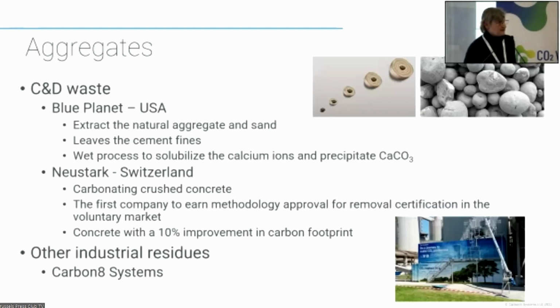So in the aggregates field, again, people using C&D waste because of it being in abundance, and Blue Planet in the USA extracting the natural aggregates and sand from the concrete and demolition waste, and then solubilizing the calcium ions from the cement fines and precipitating calcium carbonate to make nice limestone, what I would call ooliths or rounded aggregates. Similarly, Neustark in Switzerland are doing that, and they are the first company to earn methodology approval for removal certification in the voluntary market so that they can actually get value out of the CO2 that they're capturing. And they say that they can have concrete with a 10% improvement in the carbon footprint.